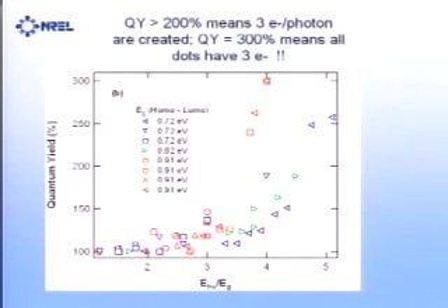And we can generate quantum yields, and this is really the most important slide, because it shows the quantum yield in percent as a function of the photon energy. And we've done many, many experiments just to get good statistics. And what you see here is the size of the quantum dot. I don't have the dimension, but this is 3.7 nanometers to 5.4. And this is the HOMO-LUMO, the effective band gap of the quantum dot.